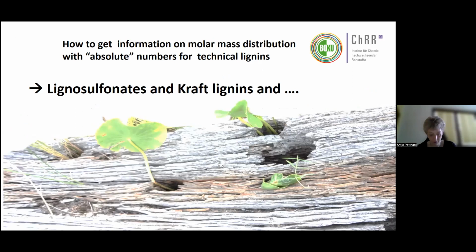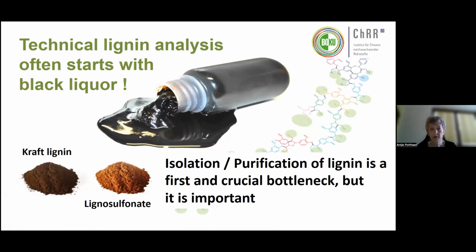What I also want you to have in mind is that lignin is a very generic name for a lot of different things. There are Kraft lignins, and there are different Kraft lignins, not just because they are softwood and hardwood and mixtures, but also because of different processes and different parameters in the same process. There are a lot of different lignins out there, and there is lignosulfonate, and there are a lot of different lignosulfonates, and there are biorefinery lignins. So it's always important that we really specify. And also for analysis, it's a huge difference if we analyze a lignosulfonate or a Kraft lignin, and I'll show you some examples afterwards. So just keep in mind, make sure you choose your method according to your lignin needs once you have to choose one.